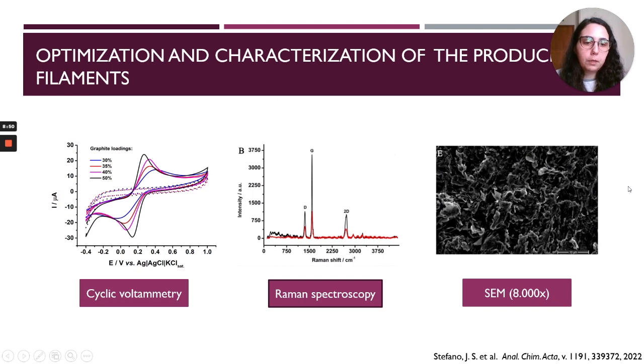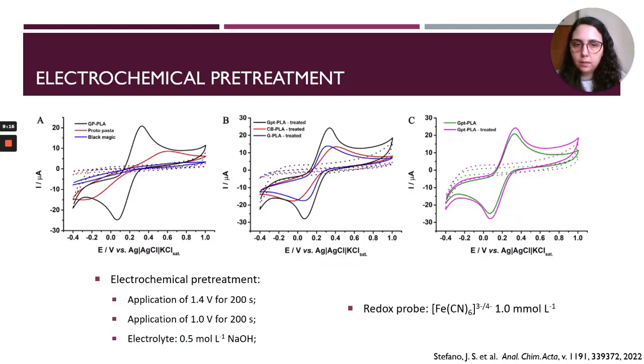We also did some microscopy. So this is SEM, scanning electron microscopy, at a magnification of 8,000 times, sorry. And we can see that there are graphite flakes all over the surface we studied, again showing that the composition of the filament was adequate, was as expected.